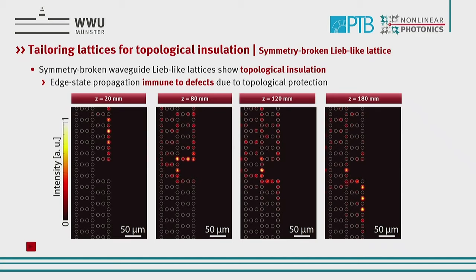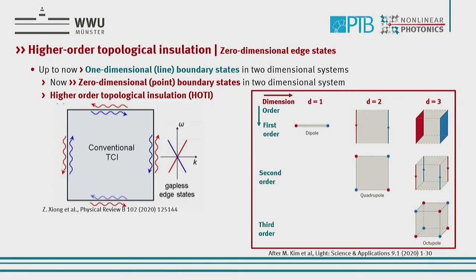And if there is a change or a defect, like it is here, then you see that the light is also propagating around the defect and stays in the same situation as topological insulation. So this is quite nice, and it proves that if you choose the edges of the real system wisely, you can always have this propagation as a topological insulation, because then your Chern number changes. You have a phase transition.